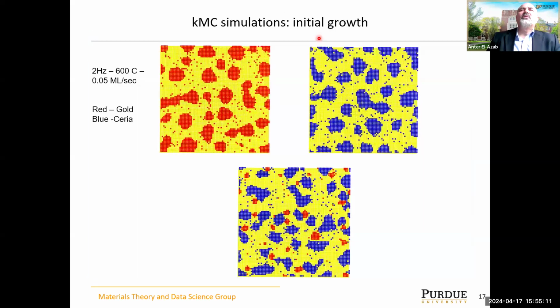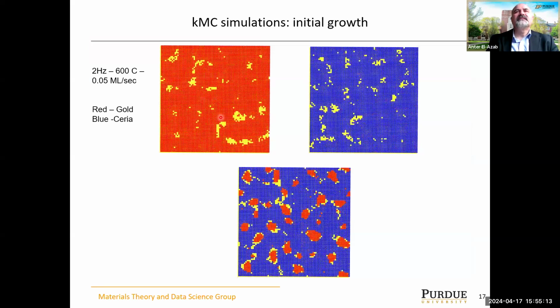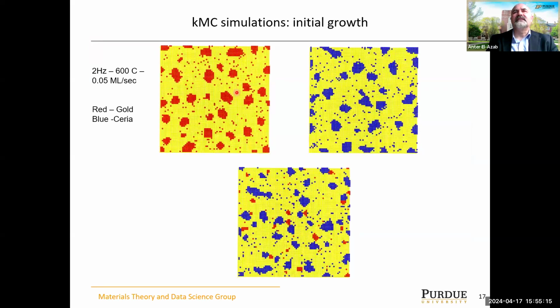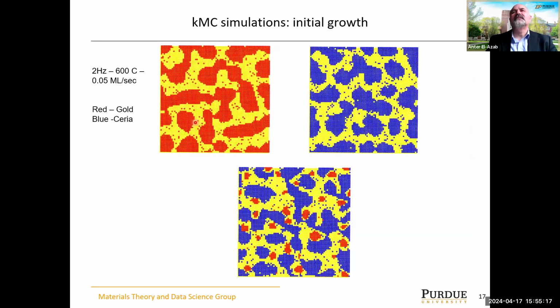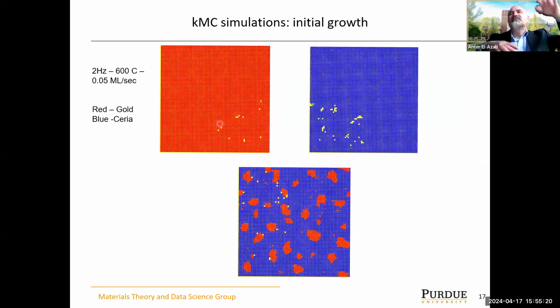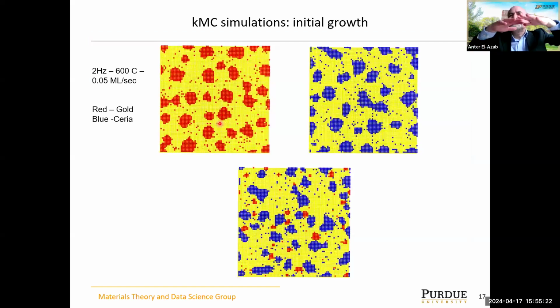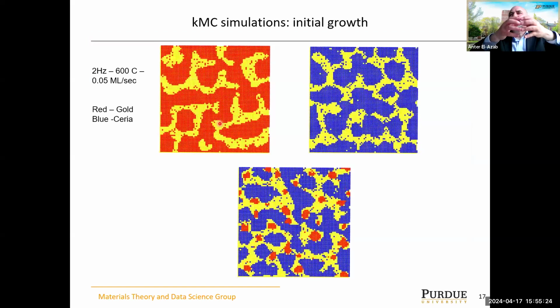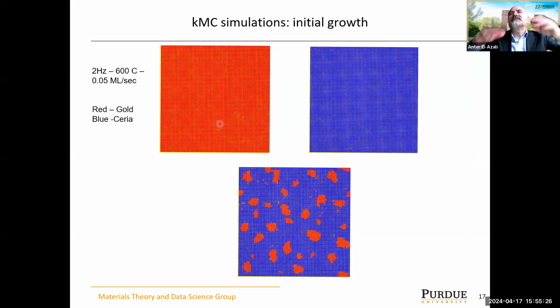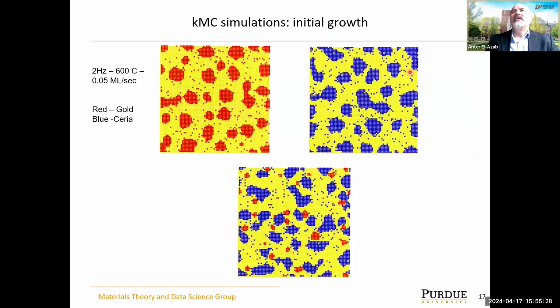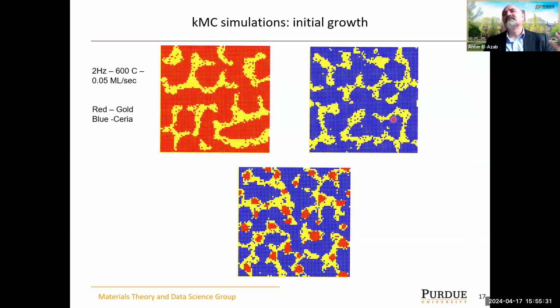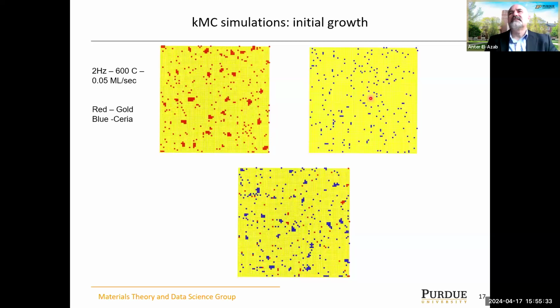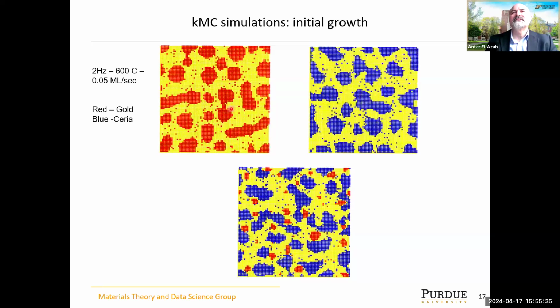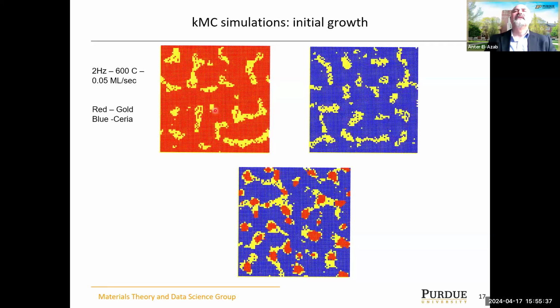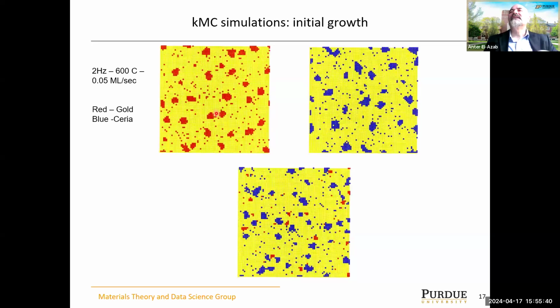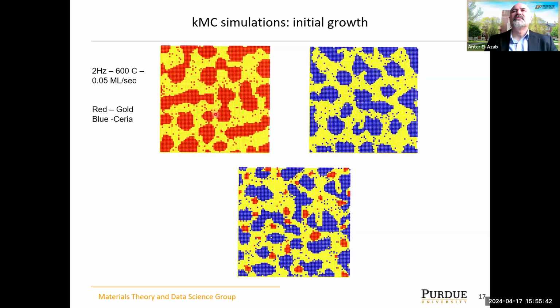If you're depositing gold only, you're going to see this red movie, gold on the substrate, and a layer is completed. You deposit in patches, and then the atoms self-organize and go in layers until they fill the surface. If you deposit the ceria, it behaves more or less the same as this one. So this is a standard or classical single phase film growth simulation that people have done.